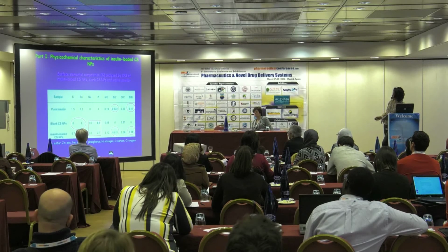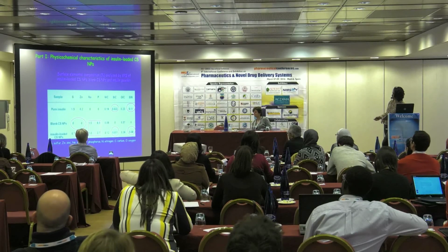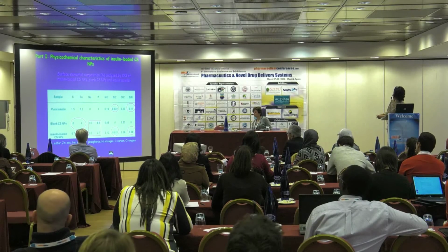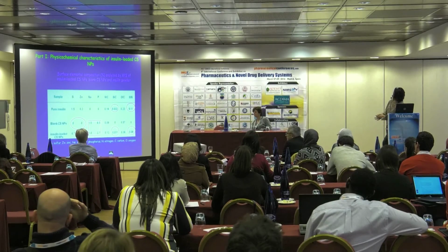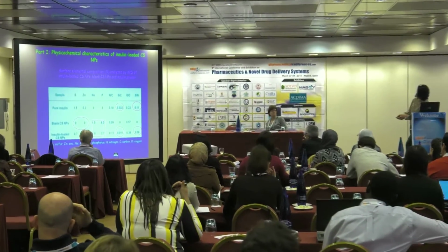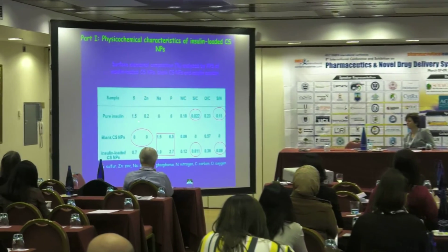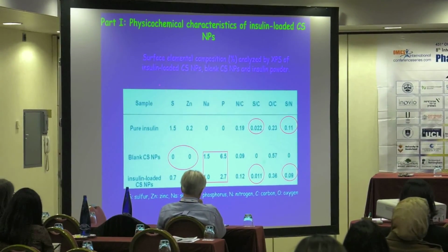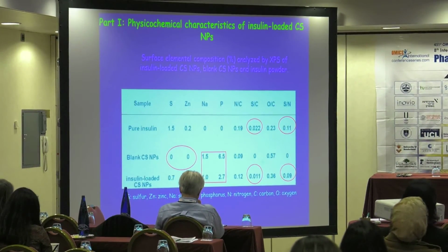Here we used pure insulin powder, blank chitosan nanoparticles, and insulin-loaded chitosan nanoparticles. We can see that in the blank chitosan nanoparticles, we didn't have any signal for sulfur and zinc, which are attributed to insulin.